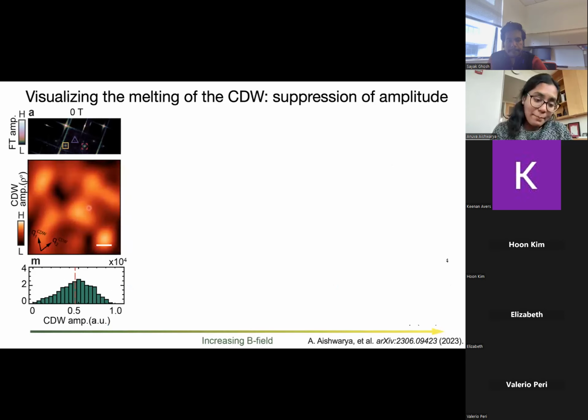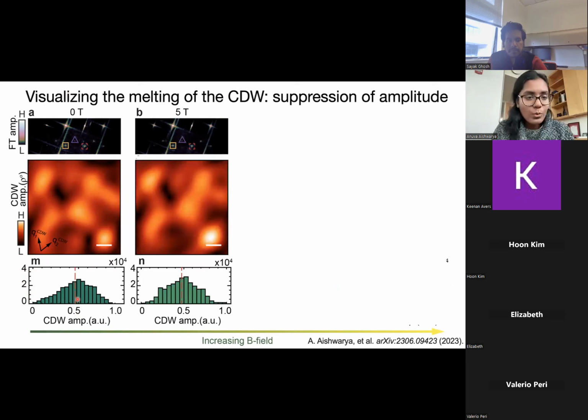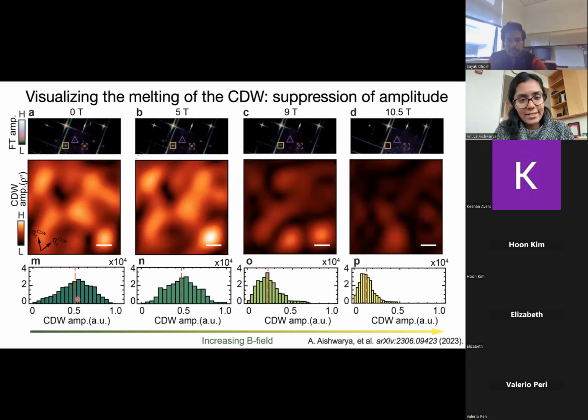Now let's look at what's happening in the amplitude as a function of magnetic field. The first is a Fourier transform. We pick out this red signal, and this is the amplitude map in real space. The bottom panel is a histogram of the amplitude, with the red dashed line being the mean value. As we increase the field, we see that the amplitude gets suppressed, and it gets suppressed non-uniformly. It's not the same image throughout getting dimmer. We see some pattern emerging here.